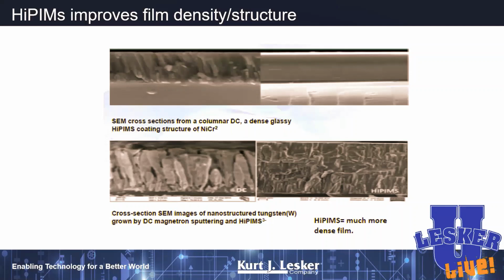And so if we look at thin film morphologies, things like nichrome by classic DC magnetron sputtering, you see the low-density columnar structures that you would normally see from that technique. By going to HiPIMS, the arriving sputter target ions are much more energetic, and so we get a fully dense film, which might even be amorphous. Same thing with tungsten. With tungsten, you see these classic low-density triangular grain structures in the films. By going to HiPIMS, much finer grain structure, much more dense film.